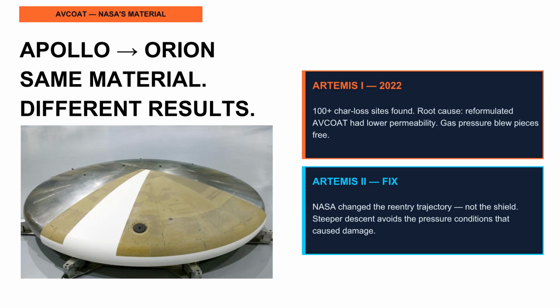AVCOAT is the ablator that carried Apollo astronauts home from the moon. It is an epoxy novolac resin filled with silica microballoons and fibers, packed by hand into a fiberglass honeycomb matrix bonded to the capsule's aluminum structure. Each honeycomb cell was injected individually, about 370,000 cells per heat shield. Apollo re-entry velocity from the moon was approximately 11 kilometers per second, faster than a return from low Earth orbit. The shield lost about 3 centimeters of thickness during re-entry. That ablation is intentional. It means the system is working.